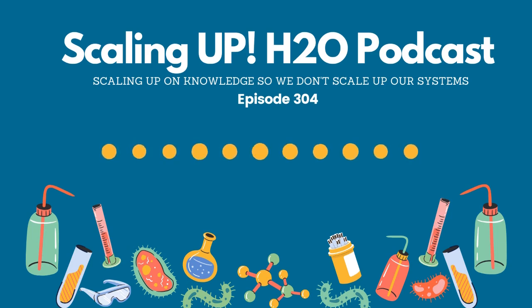And then the next 30 days, I'm going to come and I'm going to remove that set that I put in originally, but now it's been in the system for 60 days, and replace those. And now every 30 days, I have 60-day results. So that gets me a little bit more accurate, and I get a whole bunch of data points with that. Again, the more data points that we get that are accurate within the system, the better we can use these corrosion coupons to change our program, or at least verify that our program is working properly.